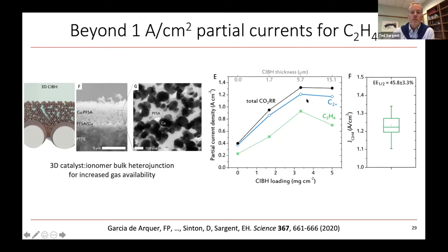And so when we did that, we were actually able to get well above 1 amp per square centimeter of current density by optimizing the loading and the thickness of the layer. And we did it while keeping a good Faradaic efficiency and therefore got to an interesting energy efficiency through this approach.